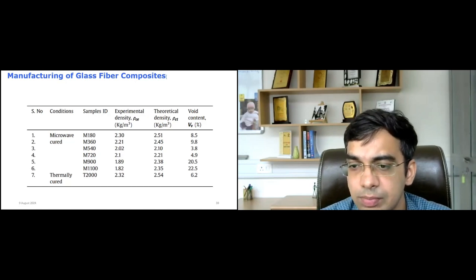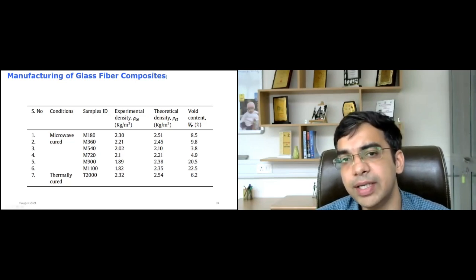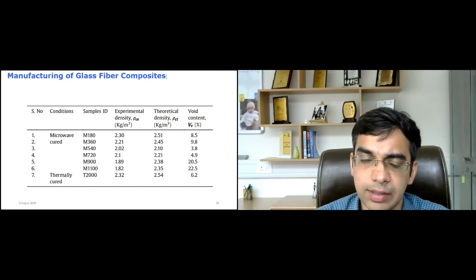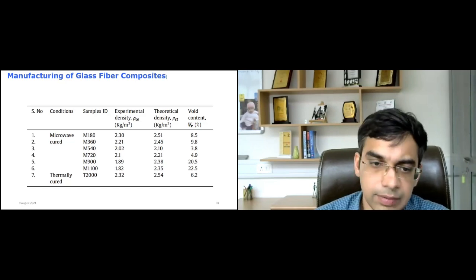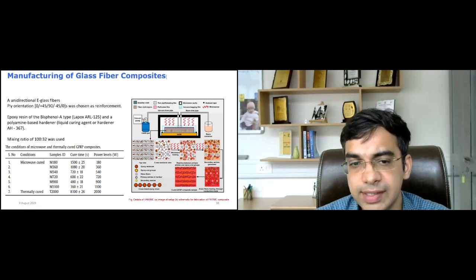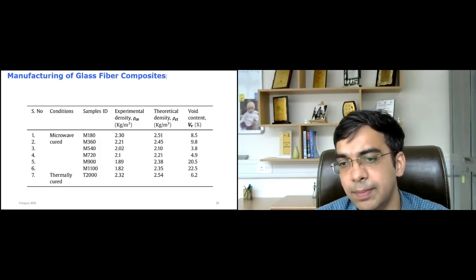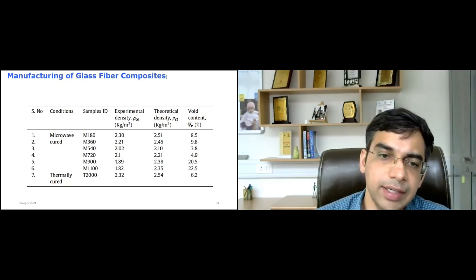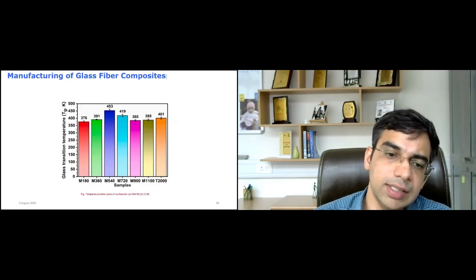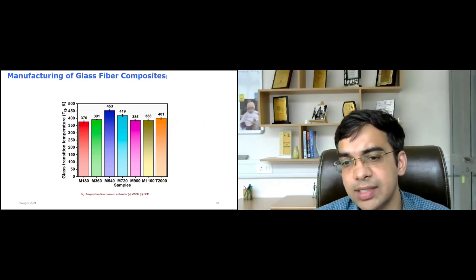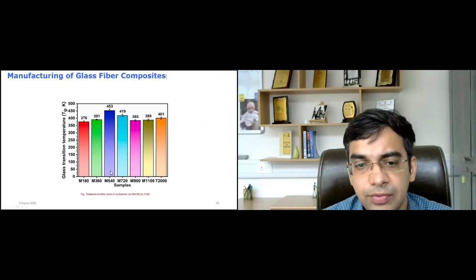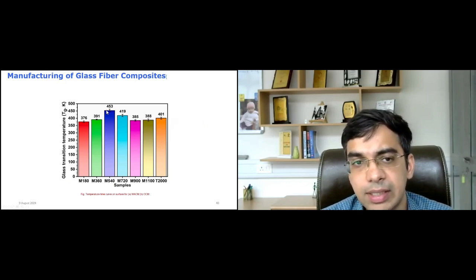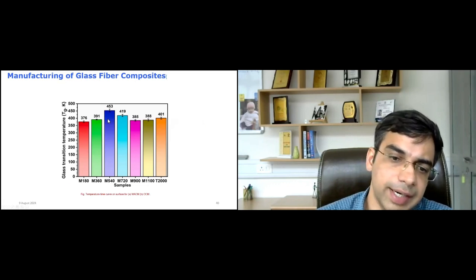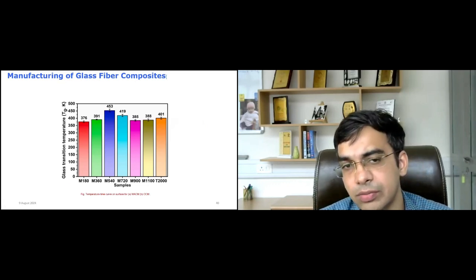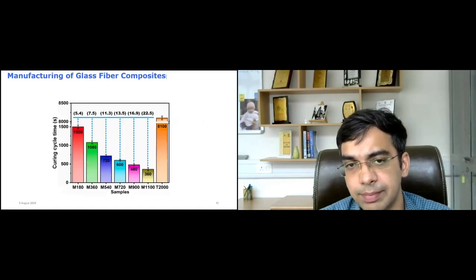So this is similar to what was observed in thermal curing, but the point I'm trying to make here is the cycle time in thermal curing was very high. It was almost 8100 seconds, and in microwave, say at 540 watt, it was almost 720 seconds. So we can see this fast cycle time has resulted in not only better quality composites, but has also helped in saving a lot of time and energy. Other than this, the extent of curing was also estimated using glass transition temperature. And what we observed at 540 watt cured samples, the glass transition temperature was much higher, and the glass transition temperature here is basically similar to what was observed in the uncured epoxy.